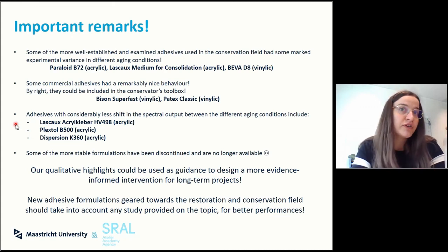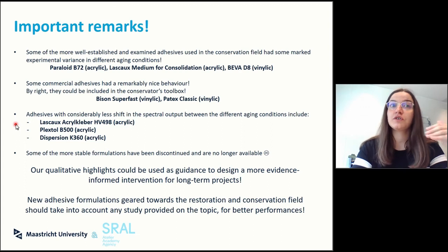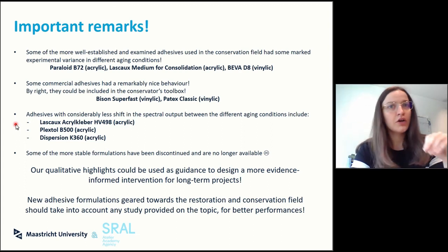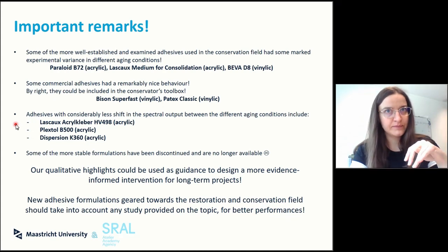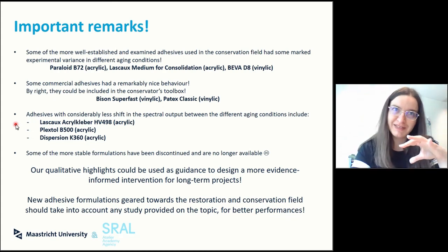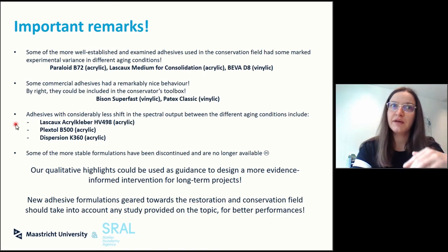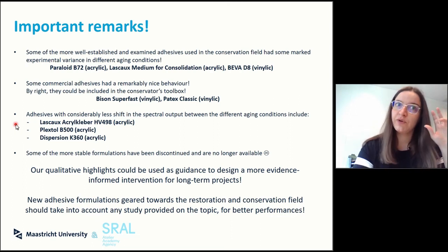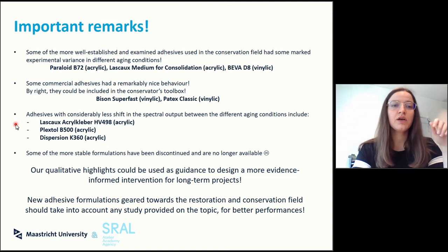And unfortunately, we have to point out that some of the best formulations that we found have actually been discontinued, and the new formulations don't seem to have exactly the same behavior. So this is also a reminder to maybe test your adhesives, even if you think the formulation should be the same. If they changed the label, they might have changed the behavior in a way that no one has bothered to flag to you in conservation conditions.